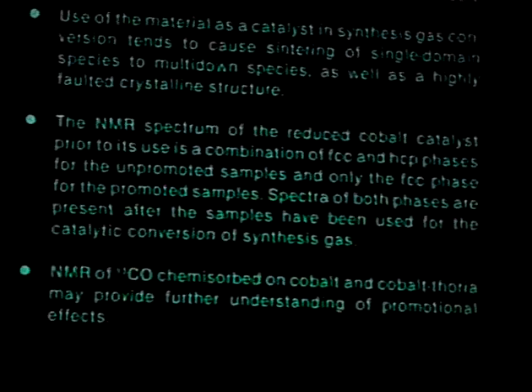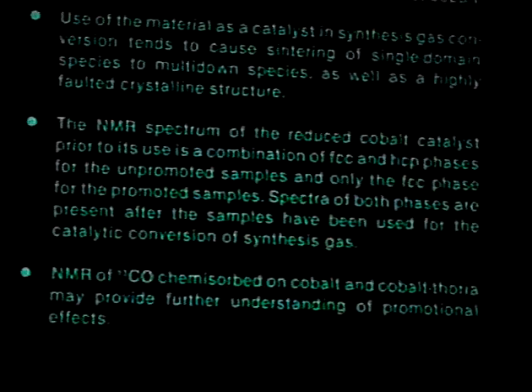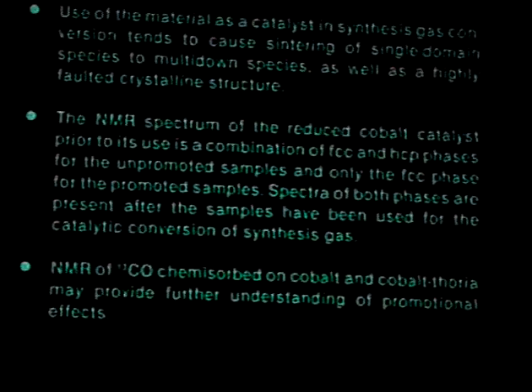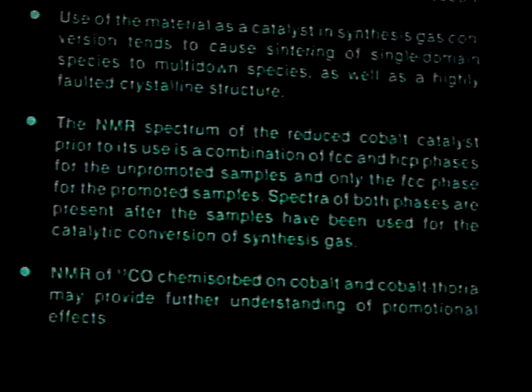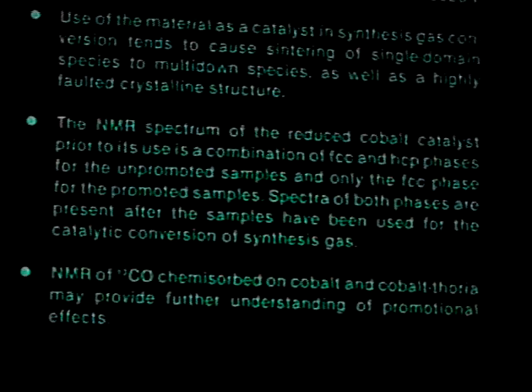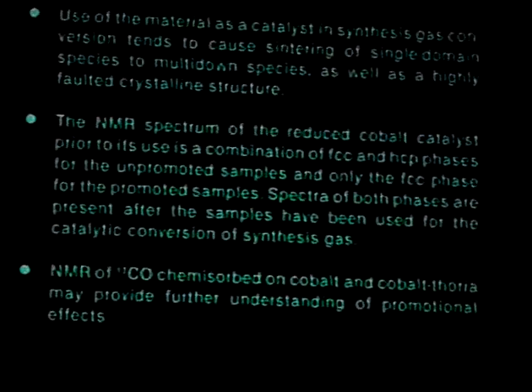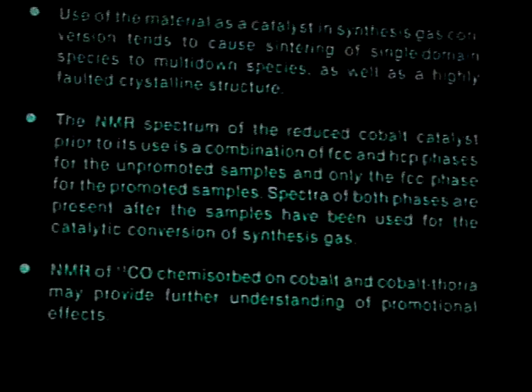Now the NMR spectrum of the reduced cobalt catalyst prior to its use is a combination of FCC and HCP phases for the unpromoted samples, and only the FCC phase for the promoted samples. So obviously the presence of thoria is inhibiting the formation of HCP phase. However, spectra of both phases are present after the samples have been used for the catalytic conversion of syngas.